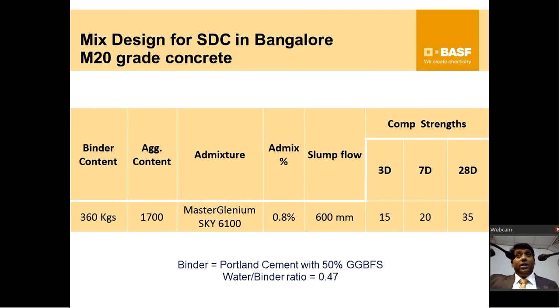Why? Not because of the flowability and other things, but because I have to pass the V-funnel test. That V-funnel test is crucial. So for SDC, smart dynamic concrete means V-funnel at the fifth minute, which I told you, and segregation resistance is important. These two are important. If anybody comes and says I also have a self-compacting concrete, ask him to prove the V-funnel test at 5 minutes, and then that's self-compacting.